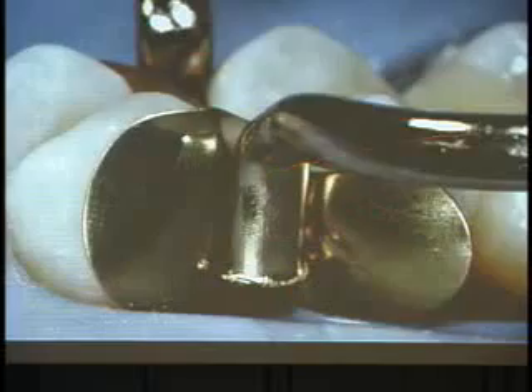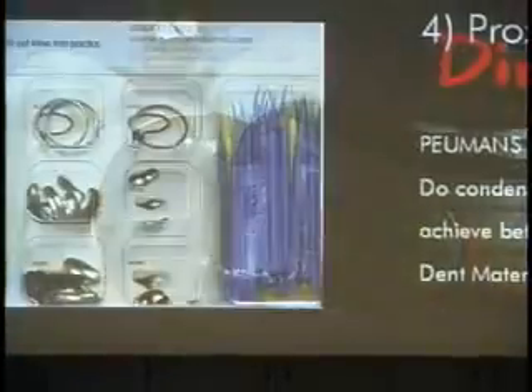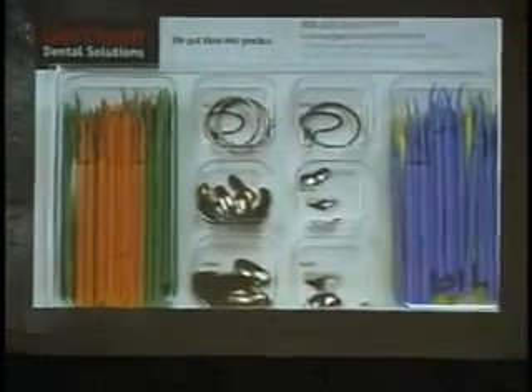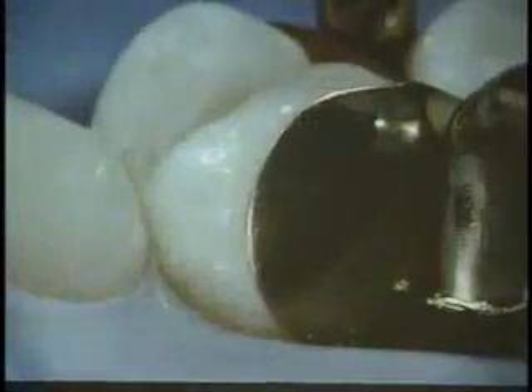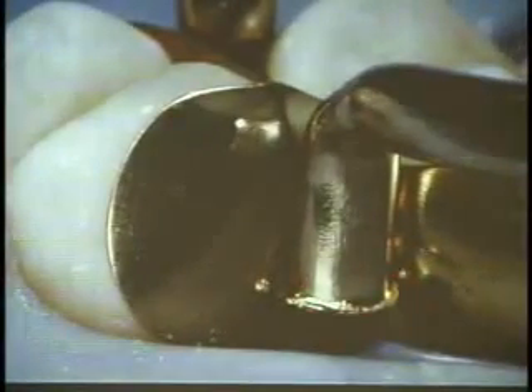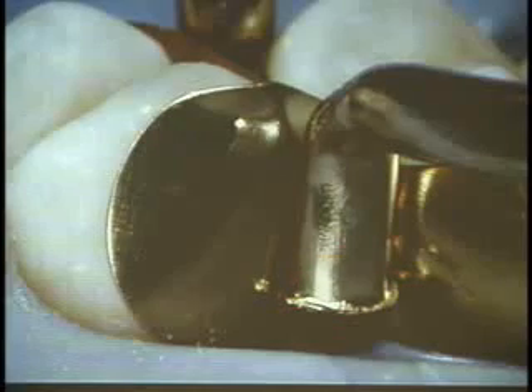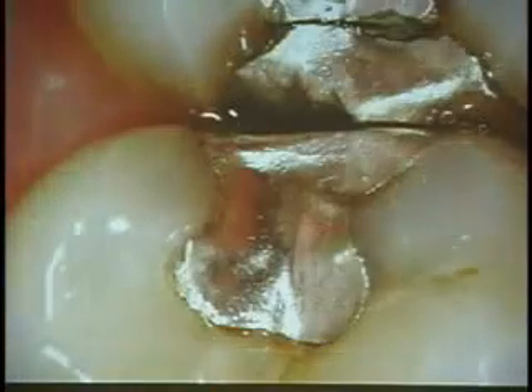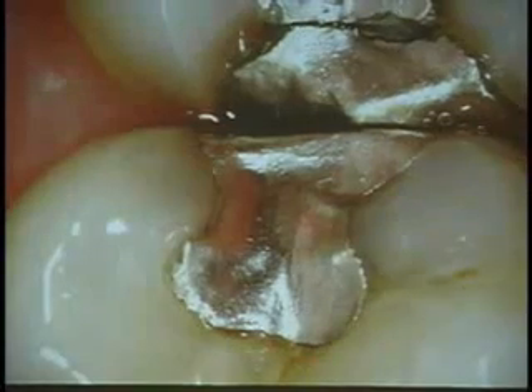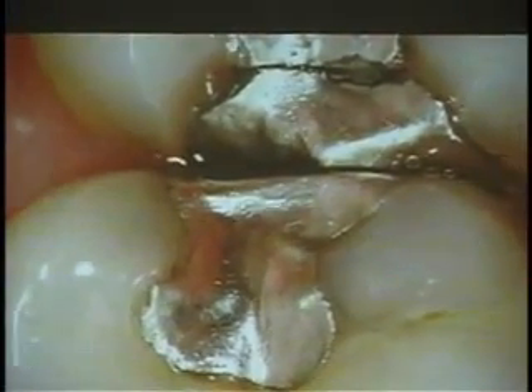And this is an example. This is the Garrison dental solution. It's again a ring, a very stiff ring, with these sectional matrices. And basically what the ring is doing with this little step here is pulling the teeth apart very, very strongly, and that gives well enough strength to develop the contact point.